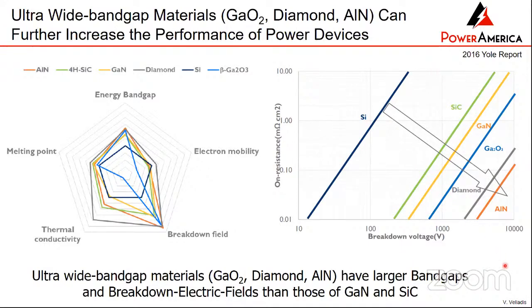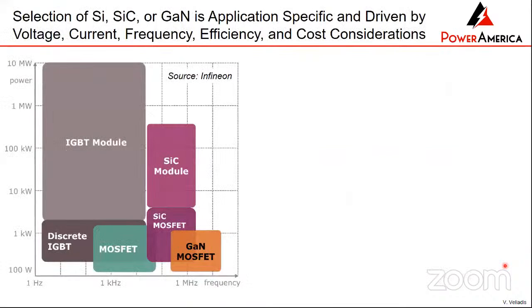Now, silicon of course is not dead, because as I mentioned before, silicon is very mature, it's very cheap, and it can be processed in fabs, foundries around the world at a very low cost. So it's a very big competitor. So where do the different materials have applications? If you look at the frequency versus the power, you can see that at low frequencies, silicon devices, the IGBT, the MOSFET, and modules do very, very well. It is when you go to higher frequencies that silicon is a lot more lossy, a lot less efficient, and that's where you have silicon carbide devices and modules. And GaN, of course, has an even higher figure of merit, so GaN can go into higher frequencies.